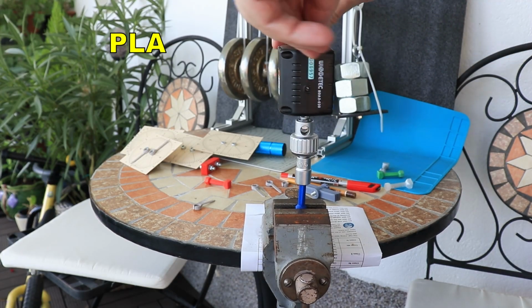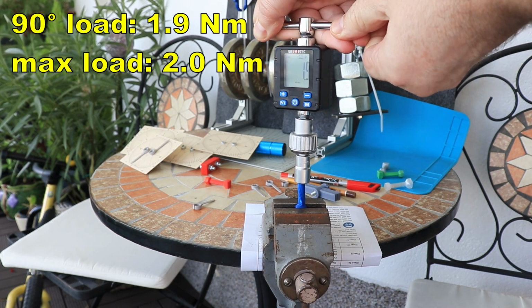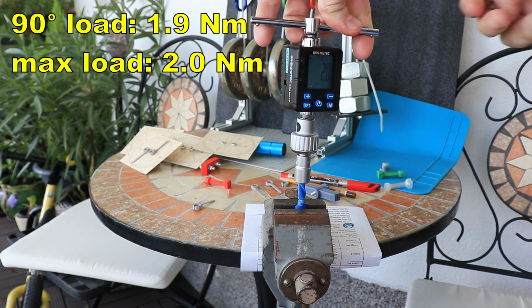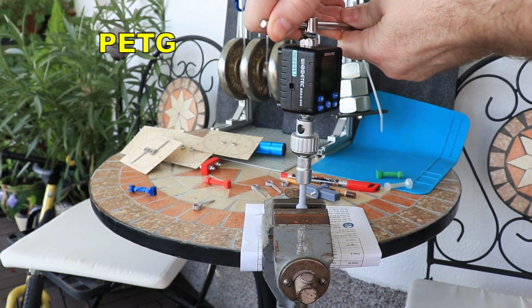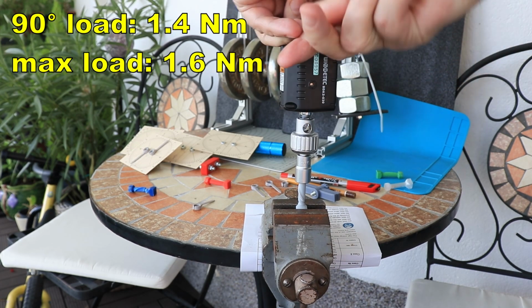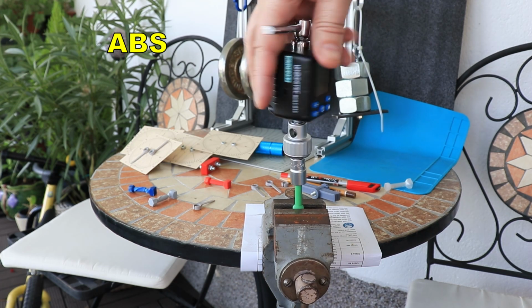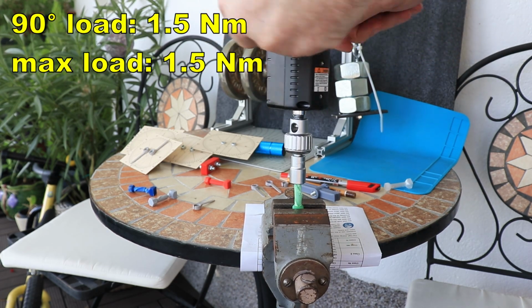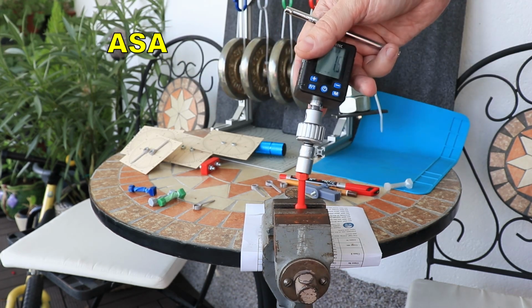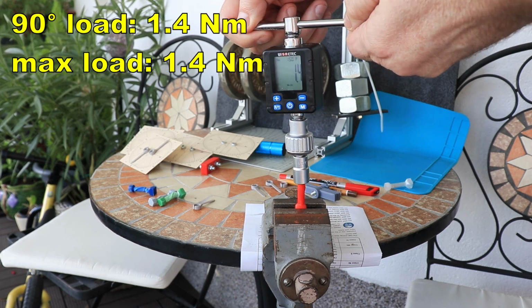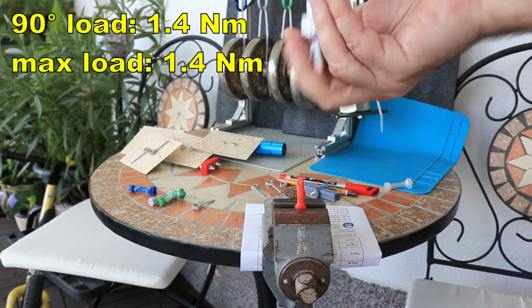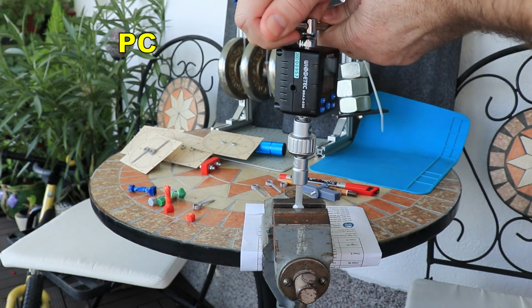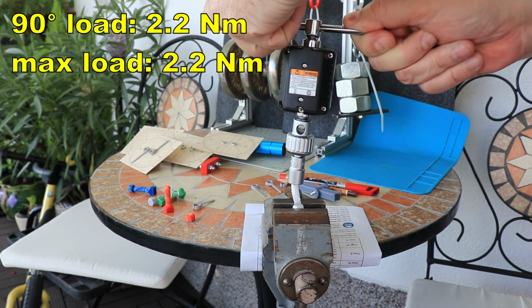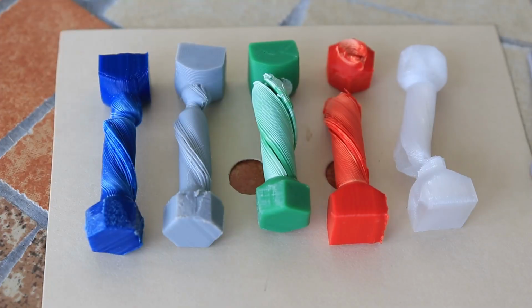PLA 1.9, 2.0 is the peak. PETG 1.4, 1.6 was the peak. ABS 1.5, 1.5 was the peak. ASA 1.4, 1.4 the peak. PC 2.2, 2.2 was the peak. For the failing, I wouldn't say there is any significant difference between them, and they all failed after approximately a little bit more than half a rotation.